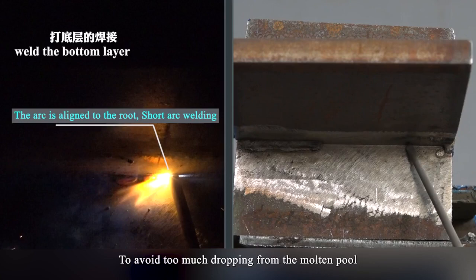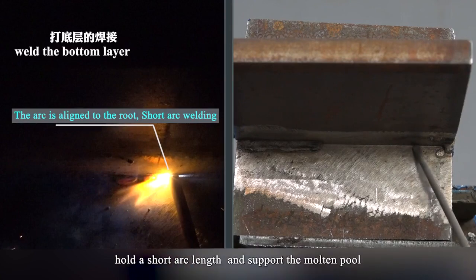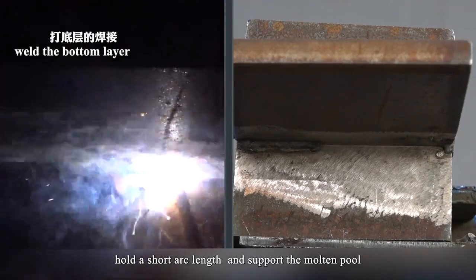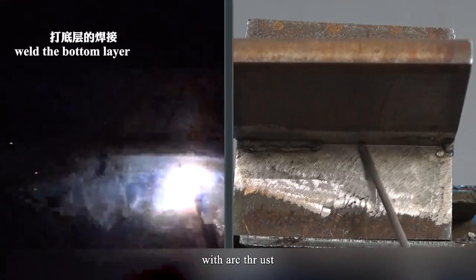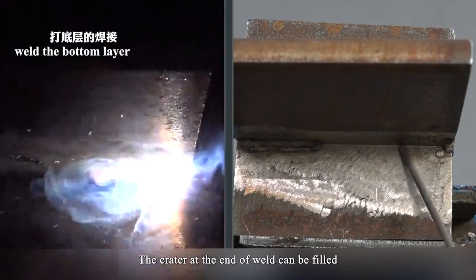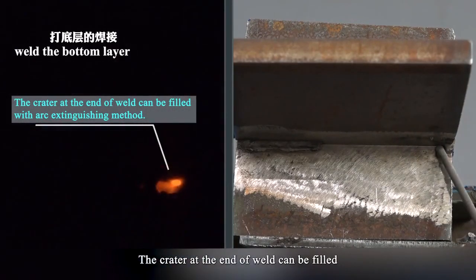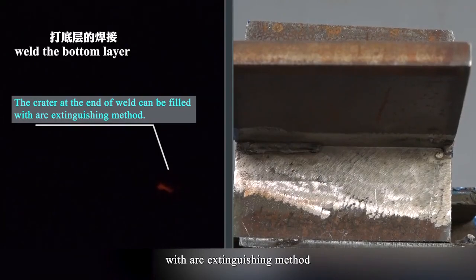To avoid too much dropping from the molten pool, which causes concave weld, hold a short arc length and support the molten pool with arc thrust. The crater at the end of weld can be filled with arc extinguishing method.